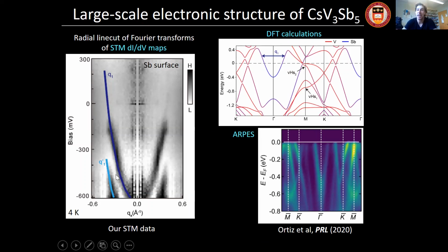So it's electron scattering and interference as a function of energy. We see nice little ripples on the surface that change the wave vector as a function of energy. This is one data set. We take a radially averaged line cut. So this is a radial line cut of the Fourier transform of STM dI/dV maps. What we'll see is essentially a nice circle that grows as a function of energy.